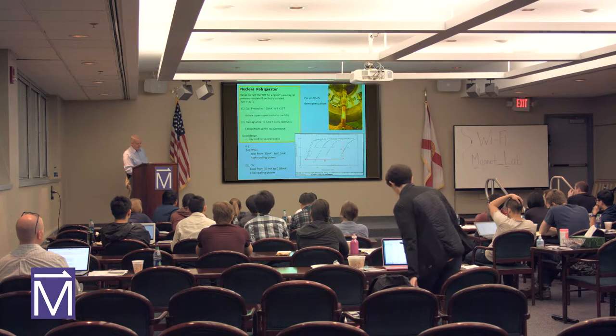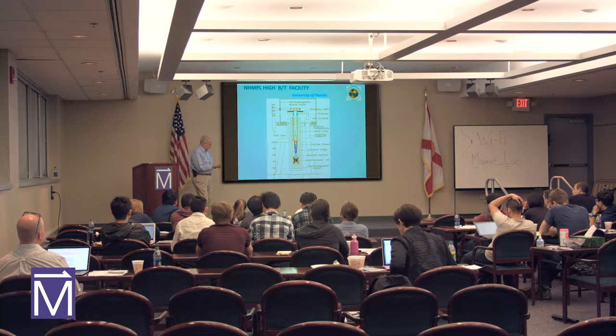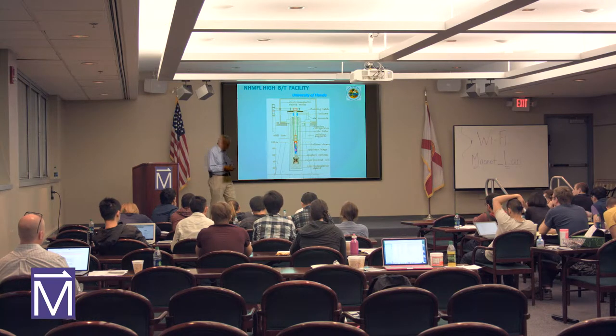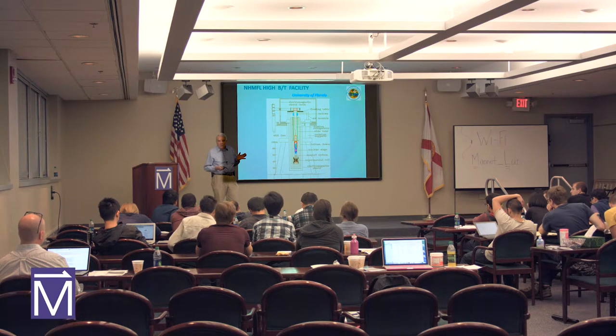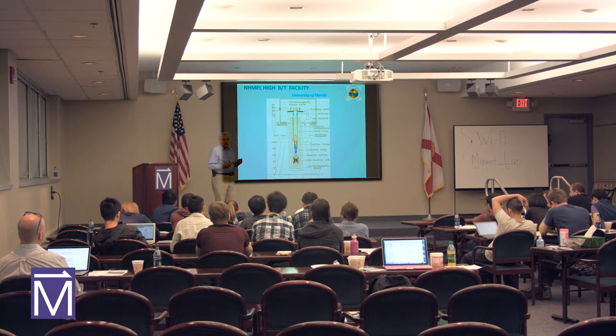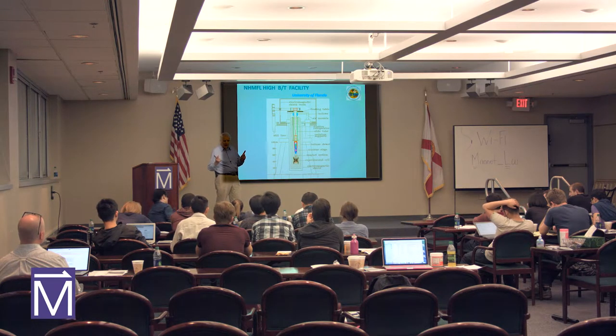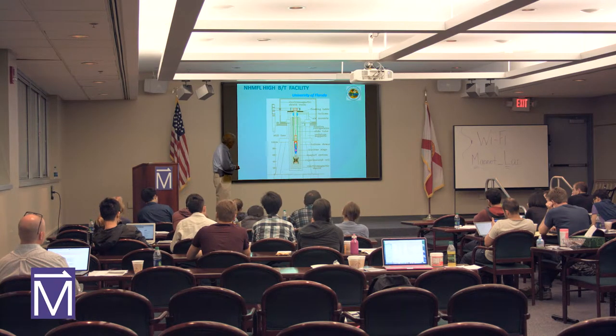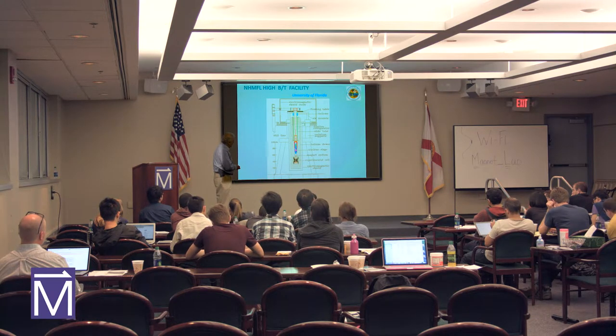Here is our nuclear refrigerator. In our most powerful case, we don't use copper — we use praseodymium nickel-5 (PrNi5). This has a very large nuclear moment with the hyperfine interaction, giving very large magnetization and more cooling power. The price is that nuclear spin ordering starts at about 180 microkelvin, so you can't get below 200 microkelvin. But users are very happy with that. The experiment magnet can get up to about 60 and a half Tesla. You can do experiments at 60 and a half Tesla, and by continually demagnetizing you can stay cold for about a month.